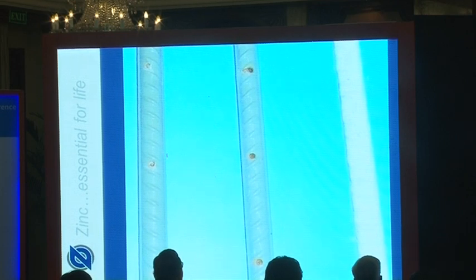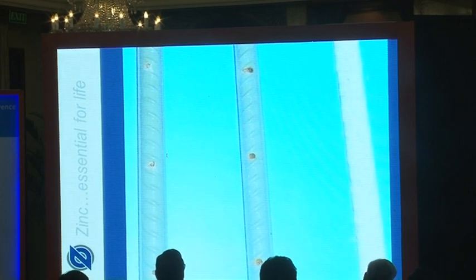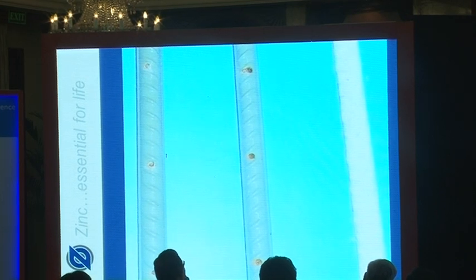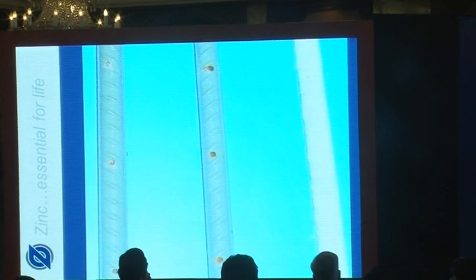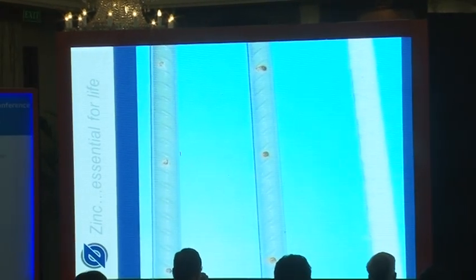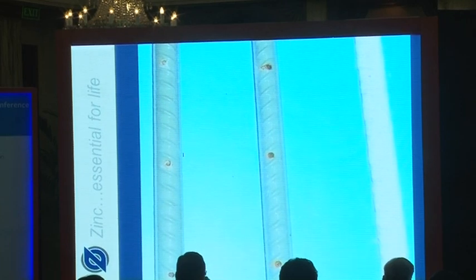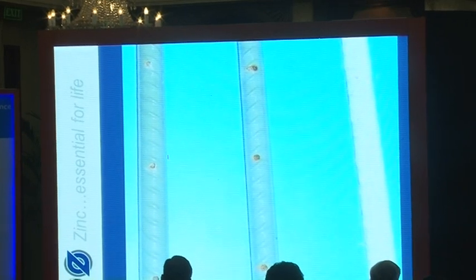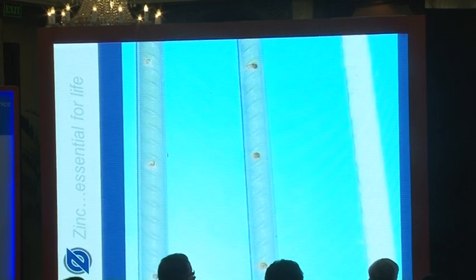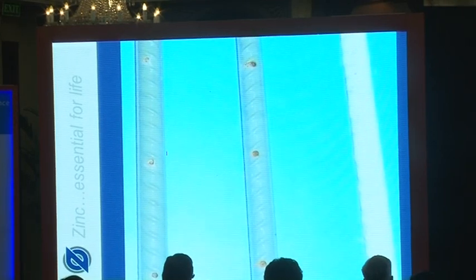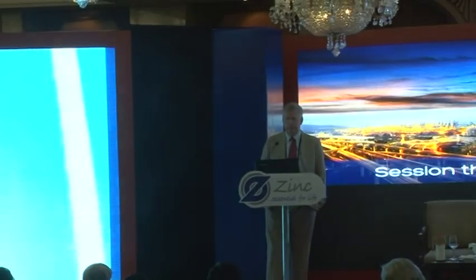In the middle, you've got the epoxy only, and we drilled holes in this to damage the epoxy intentionally, and you can see the under creepage after 24 hours only. You're starting to get red rust and a damage of the paint around there. On the left-hand side, we have the zinc coating plus epoxy, and you don't see any redness in those holes, or a very faint redness in the holes. Certainly the holes in the middle are quite red because of the steel attack, and along with the minimal iron attack on the left side one, you don't see really any edge creepage. So this shows the zinc is doing its job. It's protecting the coating from being damaged.